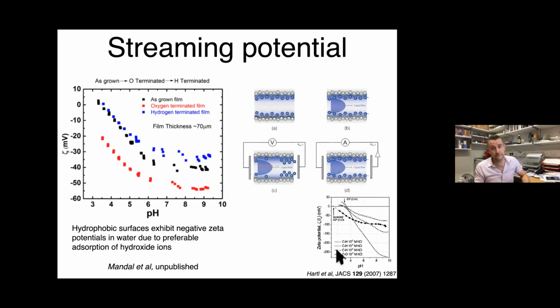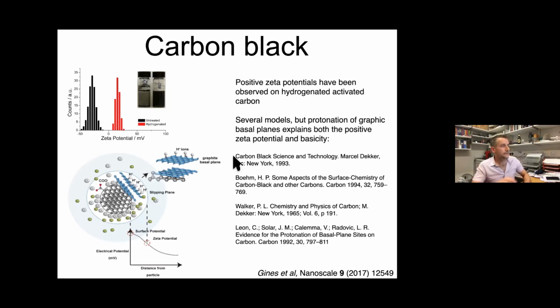But he never saw a positive zeta potential from hydrogen terminating a bulk diamond. And the final thing, I think, on the positive zeta is if you go back to all the carbon black literature. So this was something I used in a big hand wave in the paper in 2010, saying, well, it looks a bit like carbon black, which I don't think was very satisfying at the time.